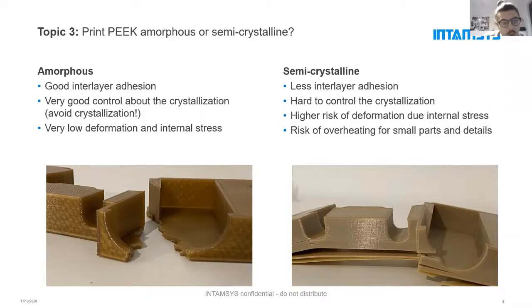When you print with an amorphous strategy, you cool the parts a little bit down. You avoid too much heat in the part to make sure that the part does not crystallize. This gives you a good interlayer adhesion. You have a very good control over the crystallization, which results in a very low deformation and low internal stress between each layer.